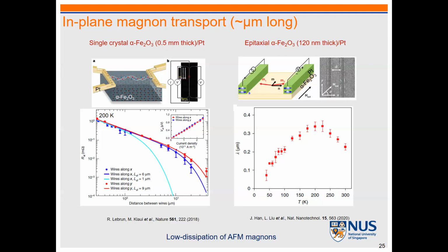So once you do XRD, we have different phases: 111, 100, 110. So it's not really a good crystal. But even so, 30 nanometer is no problem, because we are taking advantage of vertical transfer. The device length scale doesn't need to be very long. But in-plane, you have to study at least hundreds of nanometers, because your contact thickness or width is easily 100 nanometers. So the separation should be much more than that. So that's the difficulty in the in-plane geometry. That's why I think it's not useful. Hope the audience working on this doesn't mind.